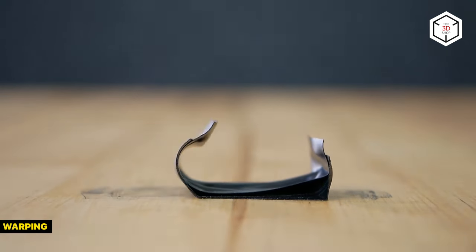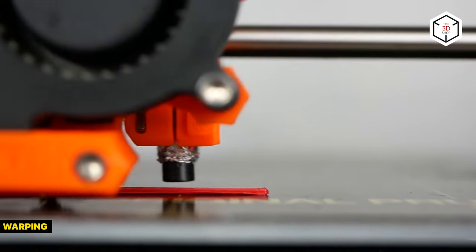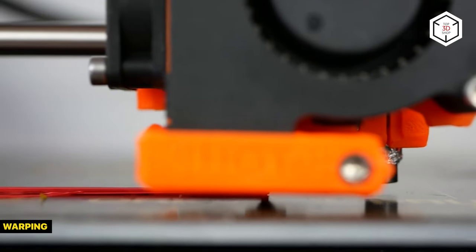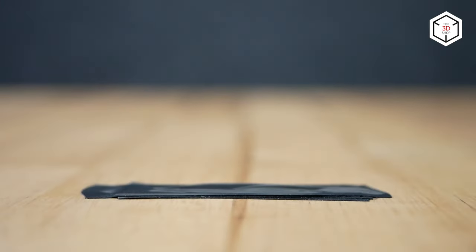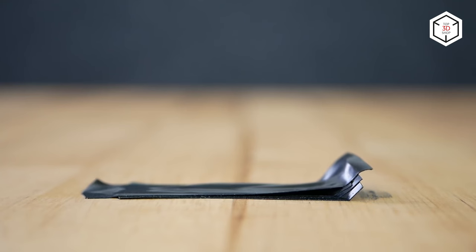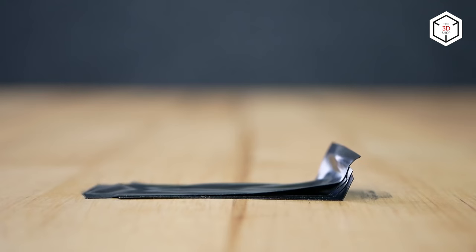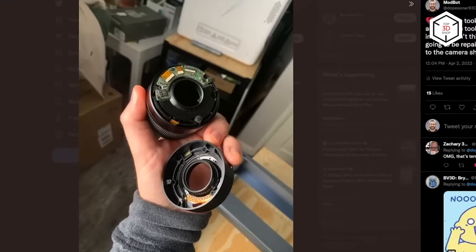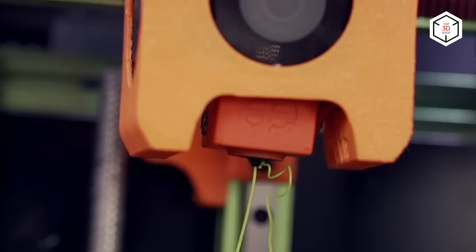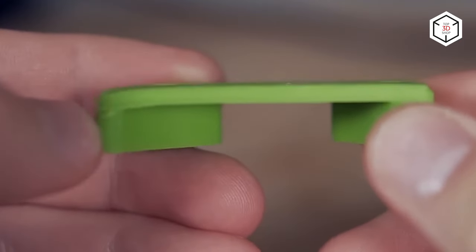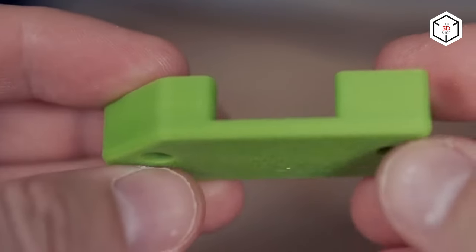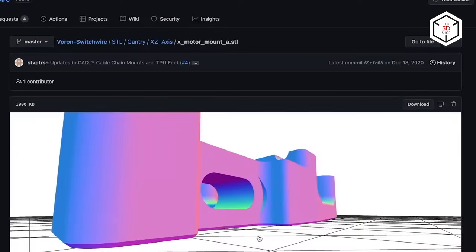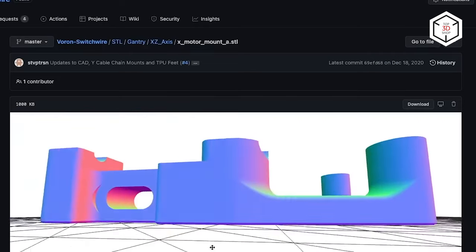Warping, one of the most well-known problems of FDM printing, requires special attention. Since the extruded filament tends to shrink while cooling down during solidification, different areas acquire varying dimensions and properties. Thus, it affects internal tensions and causes distortion of the bottom layer. Despite regularity of this process, it can be prevented by improved adhesion, close observation, and careful temperature control for the bed and build chamber.